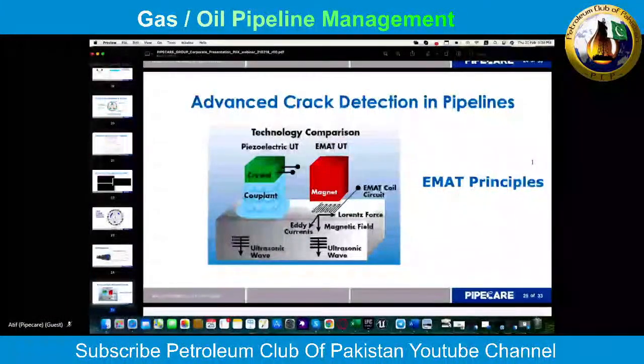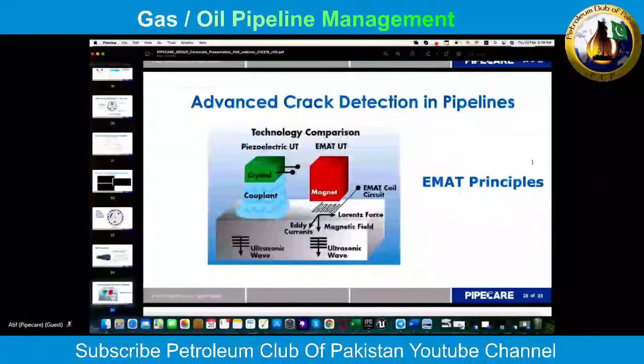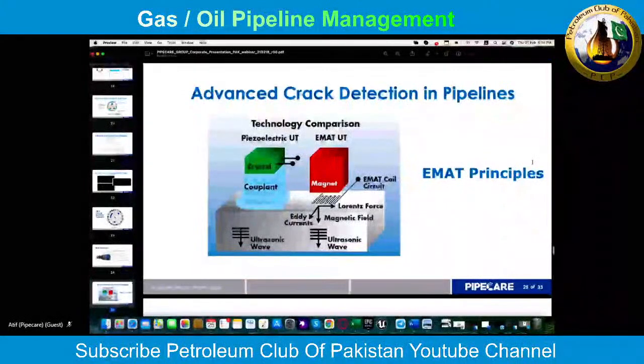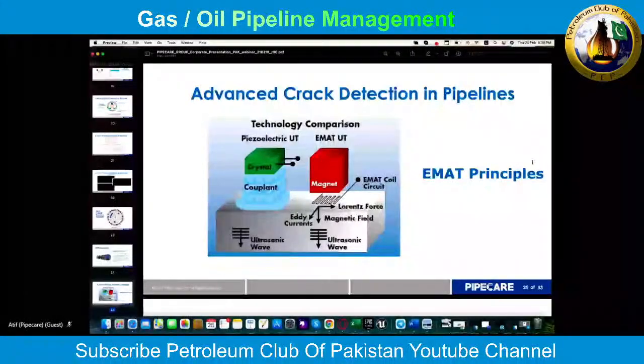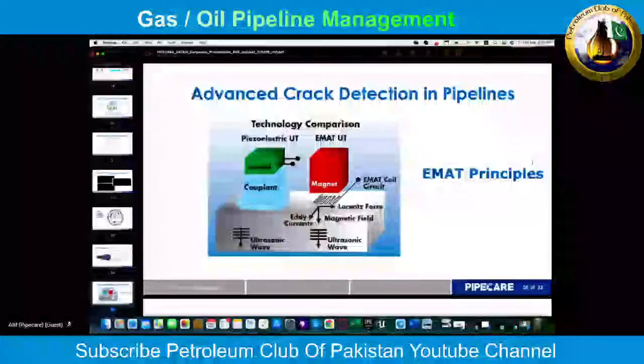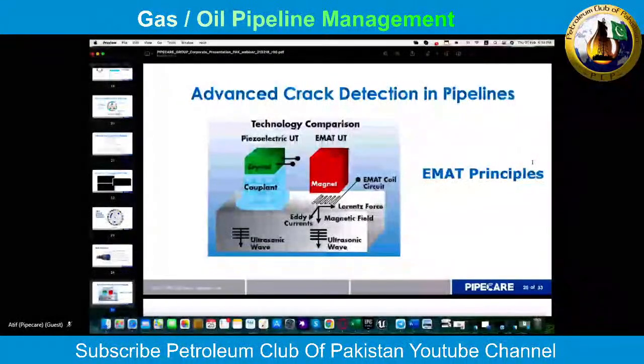The principle, or the 2 principles, are shown on this slide. On the left, the traditional ultrasonic inspection tool, where the ultrasound is created in a piezoelectric crystal and is wandering through the liquid couplant to the pipe wall, and then it works in the pipe wall. As we said, in gas pipelines, we do not want to have a liquid couplant, so the EMATS tool has to create the ultrasound inside the pipe wall. And this is done with the use of magnetic and electromagnetic fields. Next slide, please.